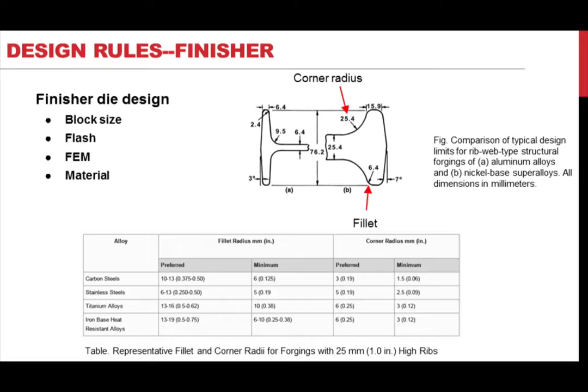Once having the geometry of the desired forging part, the die designer first designs the finisher dies by selecting the appropriate die block size, the flash dimensions, and estimating the forging load and stresses using FEM to ascertain that the dies are not subject to excessive loading. Also, there are limitations of part design, including the corner and fillet radii, which are usually due to the material and the shape of the workpiece.